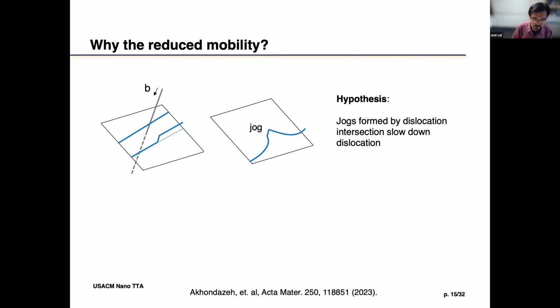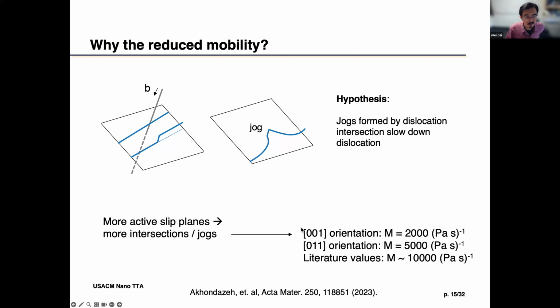There have been early studies of how jogs might affect dislocation mobility. Now, that seemed to make sense because the 001 orientation is a highly symmetric loading orientation. So the dislocations on all planes are activated and they're all cutting each other. So you can imagine there will be more jogs. Whereas in the 011 orientation, there are only two planes that are activated. So there are fewer jogs. So if the jogs are slowing down dislocations, then this could be an effective parameter that is trying to capture the physics that's missing, because in the DD simulation, we didn't consider jogs, because it's very challenging to consider their atomic size. So we didn't consider that, and most people doing DD simulation didn't consider the jogs. And then in order to agree with the experiment, I think the model is trying to compensate for that by using a lower mobility. So that is what we hypothesized.